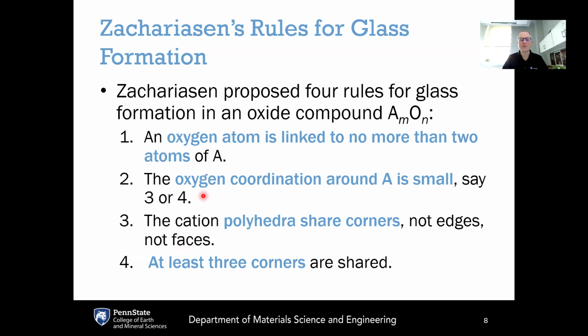So rules 1 and 2 define the basic structural unit. That basic structural unit is referred to as a polyhedron. This might be a tetrahedron, for example, in the case of silica, SiO2. A tetrahedron would have the oxygen coordination number of 4. It could also involve triangles, which would have a coordination of 3. So the general word for that is a polyhedron, and the plural of that is polyhedra. So this third rule here is that the cation polyhedra share corners, not edges, not faces.